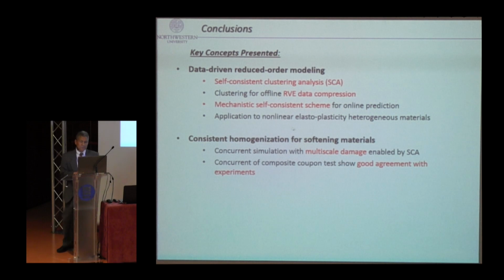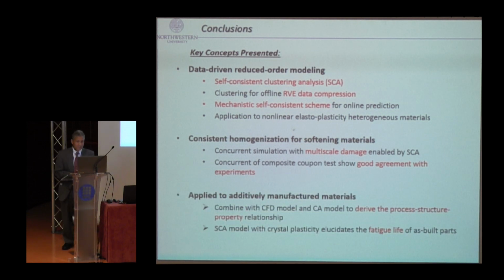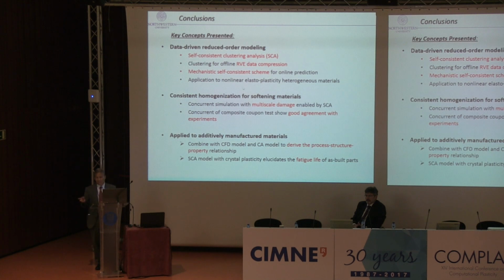And I have not talked too much about softening, which is a very complex numerical technique. For this, we come up with a method where we break down the RVE computation into 3 steps to bypass the solving numerical issue. So this is a numerical problem, not the mechanics system. And we apply this to additive manufacturing. In fact, it will be hybrid manufacturing. So we combine with CFD and a lot of other things I have not talked about to derive the process-structure-property relations. But this has to do with a lot of the material science aspect, not just computation, because some of them are an experimental database. You need to come up with the experimental database on it. And we provided the self-consistent analysis model with crystal plasticity to look at the fatigue life prediction of as-built parts.